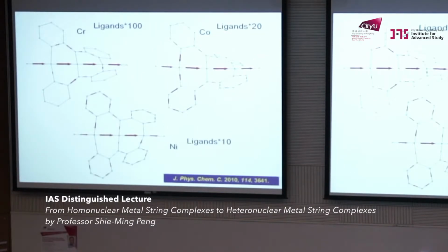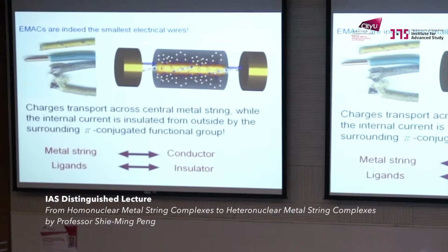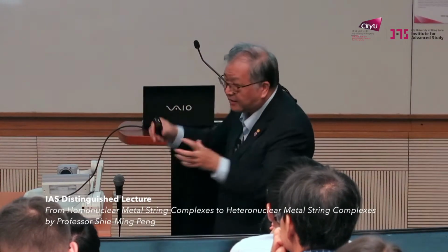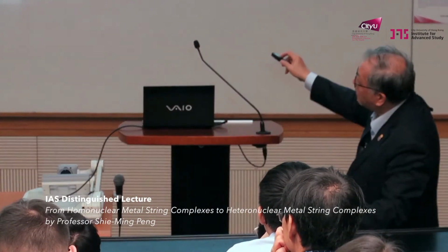Once you have the theoretical model, you can do local current analysis, to see how electrons go through the metal string. And the answer is that 99% of the electrons go through the metal string. Only less than 1% goes through the ligand. This is already times some factor. So we really can claim that our metal string is the smallest electric wire. That means a single atom wire, and the ligand acts like an insulator, as in the bulk. So this mimics a microscopic copper wire down to the atomic scale. Okay, single atom and the quadruple ligand, it acts like an insulator, and we claim this is the smallest.